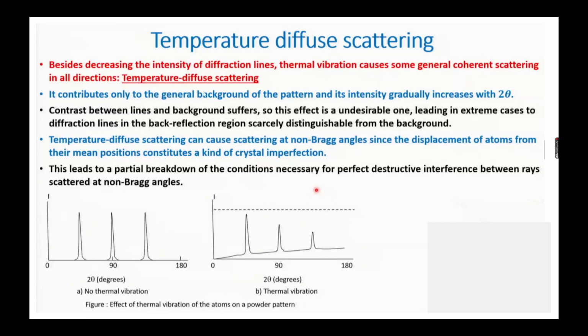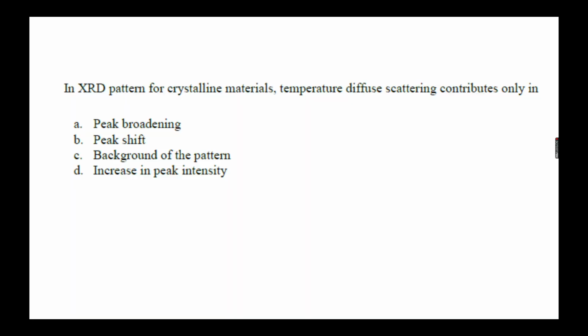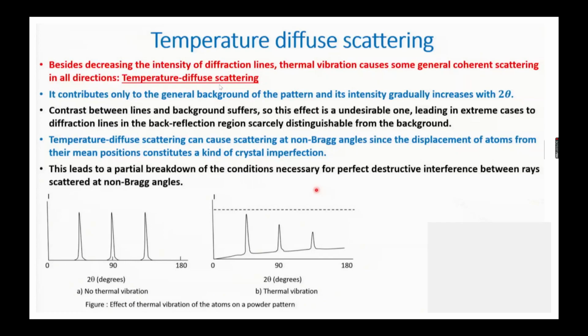So here the temperature diffuse scattering is what? Thermal vibration. If there is thermal vibration, that causes some general coherent scattering in all directions, which is nothing but the temperature diffuse scattering. And it contributes only to the general background of the pattern. So here it is asking how it will contribute, and it will contribute to the general background of the pattern, and its intensity gradually increases with 2 theta. As you can see, the background is changing, because here it is a straight line, but here it is changing, and also the intensity is increasing slowly with 2 theta value.